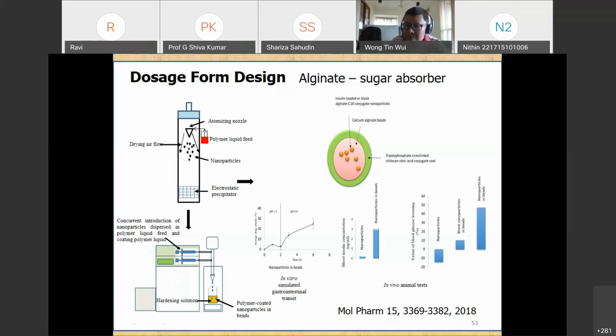And looking at the in vitro drug release data, however, we found something unexpected. Now you can see that our coated beads structures are able to reduce the early release in the gastric regions. However, in the intestinal regions, only about 30% of the insulin is being released. But nonetheless, a high bioavailability of insulin is observed in the in vivo study.